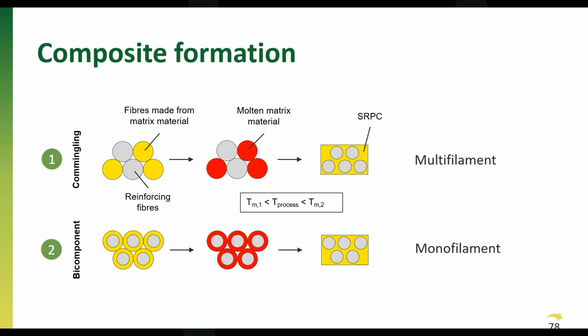Now, first of all, how is a fiber reinforced composite made within the project? We have 2 different routes. Either we go for commingling or we go for bicomponent melt extrusion. The first one is we produce separately the high and low melting yarns. In a process, we combine them, so in one yarn we have both low melting and high melting materials. Then we melt the low melting ones, the yellow ones in the graph. We have a processing temperature in between both melting temperatures, so that we don't melt the reinforcement yarn, of course. And then with again some pressure and temperature, we form the self-reinforced composite material.